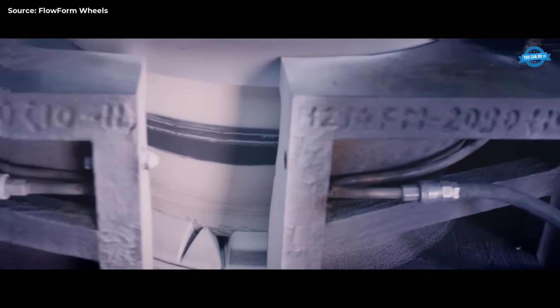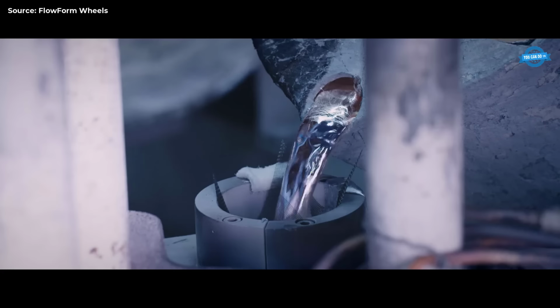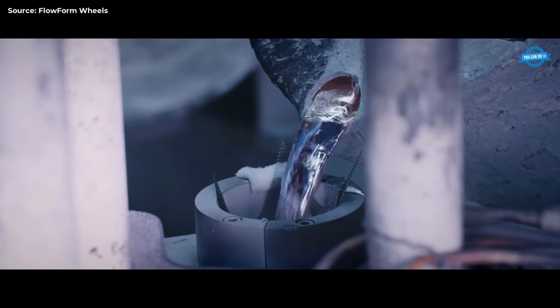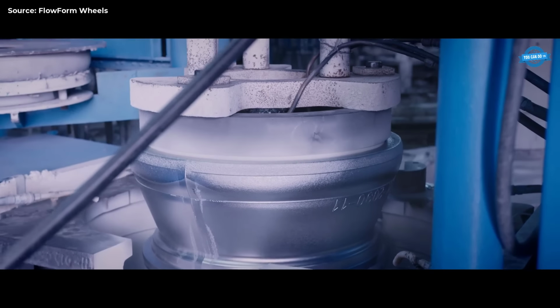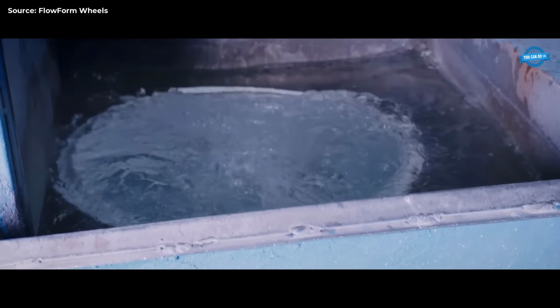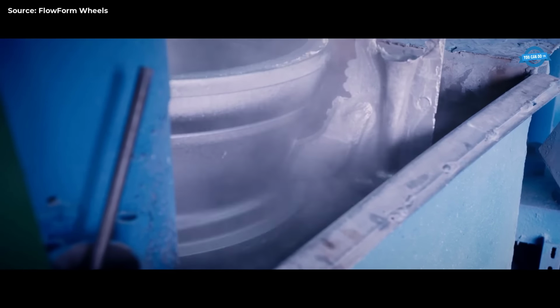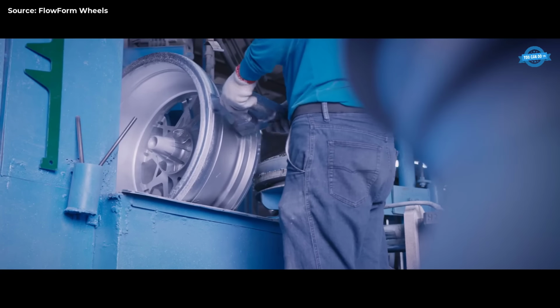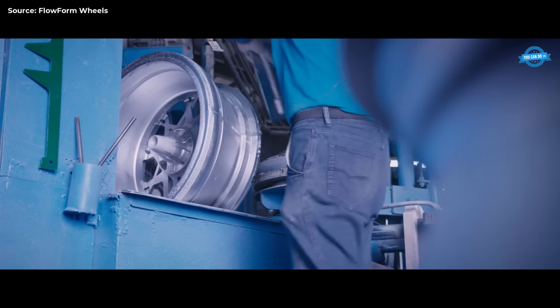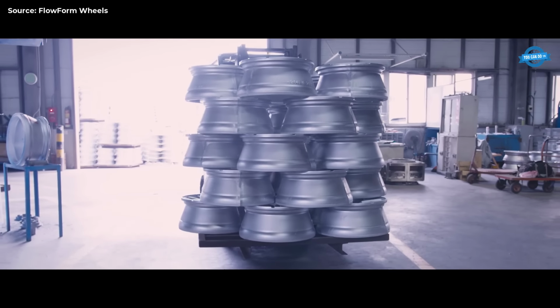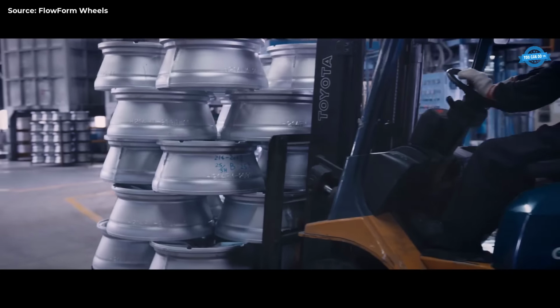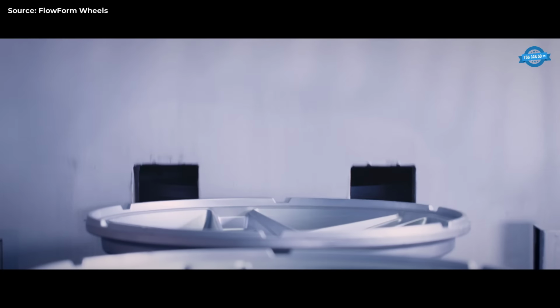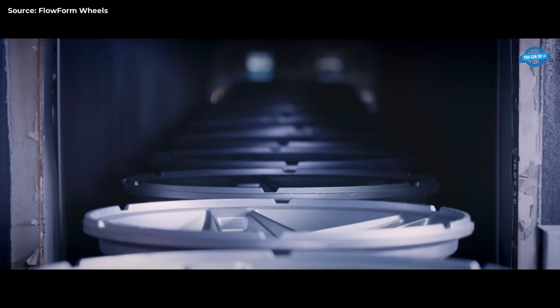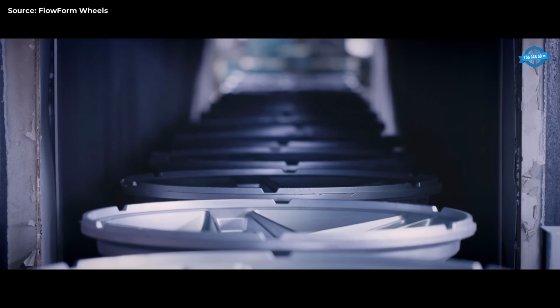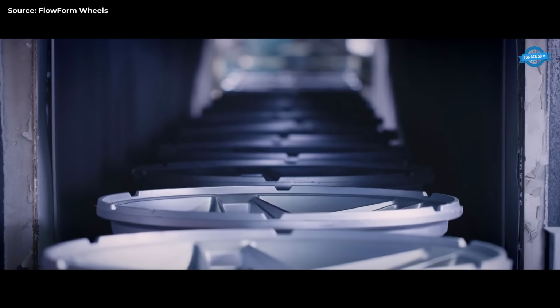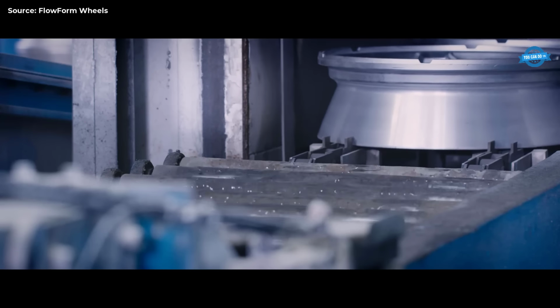Depending on the mold size, 50 to 100 pounds of molten aluminum at over 1,300 degrees Fahrenheit is poured into a steel mold, where the wheel's face is positioned at the bottom for stronger structure formation. Once the casting solidifies, it is quenched in 120 degrees Fahrenheit water, trimmed and measured to confirm correct dimensions. The initial casting features a thick skirt that will be later flow formed into the final rim shape, enhancing the crystalline structure and strength of the wheel.